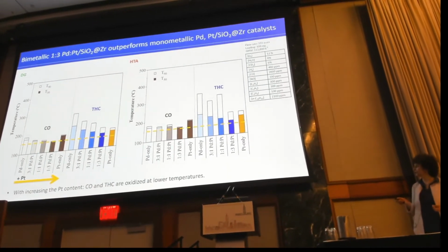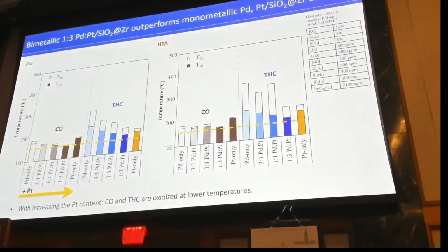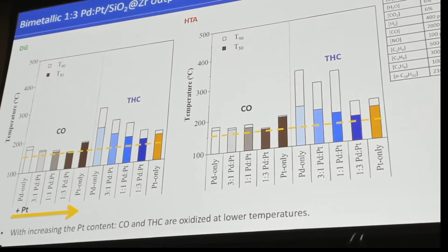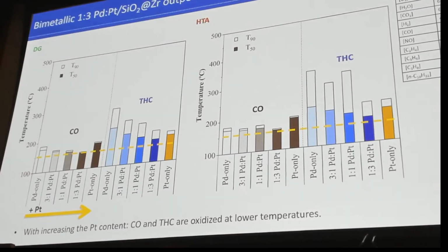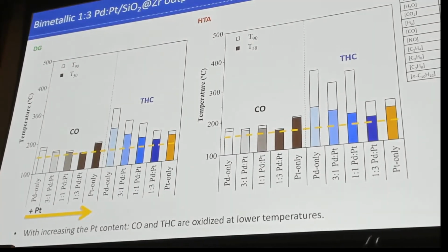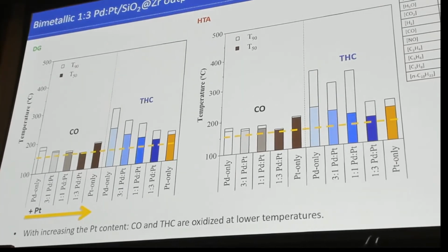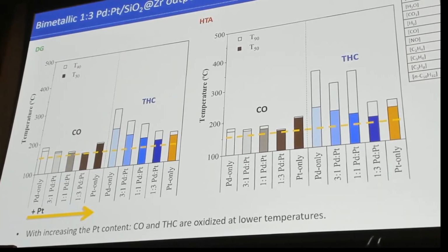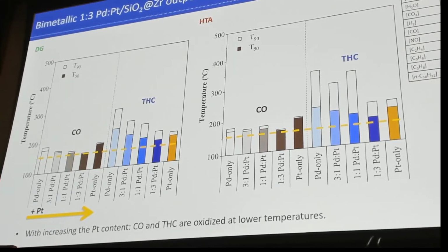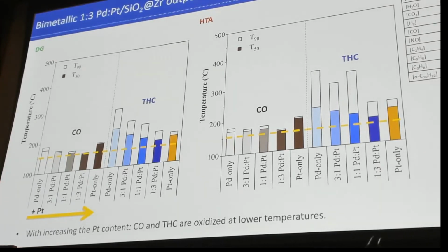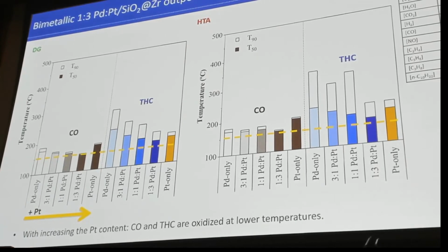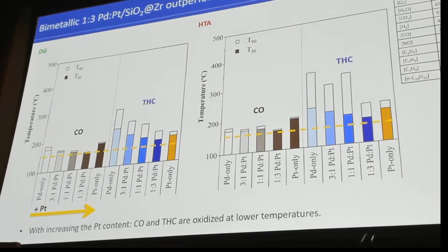So before I go to TEM images, I want to summarize a little bit the results that I showed you so far. So this figure here shows the T50 and the T90. So basically, it's the temperature at which 50% and 90% conversion of CO and other hydrocarbons occurs, when the catalyst is green, and when the catalyst is hydrothermally aged. So the x-axis shows the catalysts that we started with, and from left to right, we increase the platinum content.